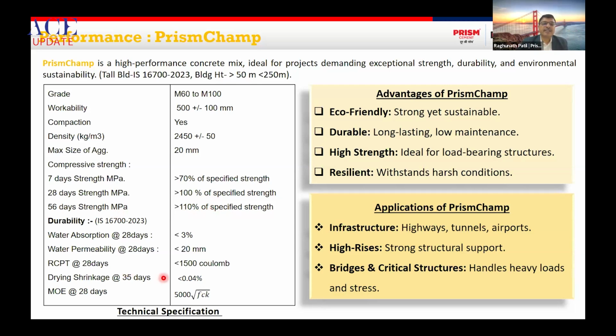For durability parameters, we generally target water absorption less than 3%, water permeability less than 20, RCPT less than 1500, and dry shrinkage 0.04%. And the modulus of elasticity is 5000 root fck. Those are the values we generally maintain while designing the mixes. Here we use highly water reducing admixture and some ultrafine material, which helps to react quickly and give early strength, and it makes the concrete very strong. These are some of the advantages.